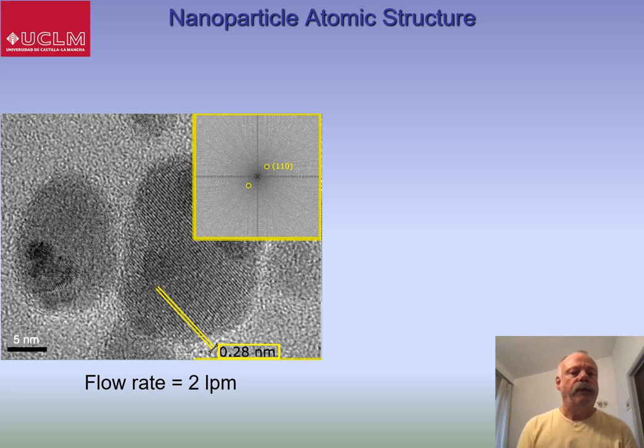Looking in more detail at the silver nanoparticles themselves, this is a TEM image of some silver nanoparticles deposited on a TEM grid. And although changing the source conditions didn't seem to change the size distribution very much, the source conditions in terms of the flow rate did seem to change the crystallinity of the nanoparticles. So, for example, at low flow rates, we get predominantly single crystals, and that's shown by the pair of spots in the diffraction, in this case, corresponding to the 110 silver lattice planes.